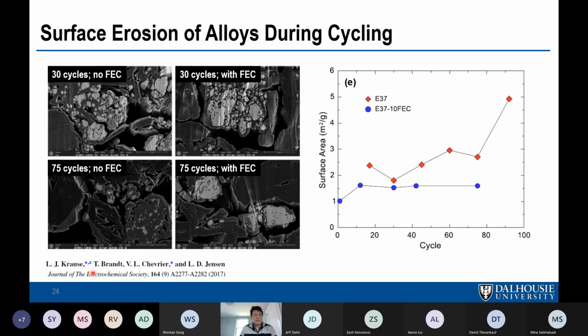This is a paper by Larry Krause and Vincent, and I don't know, Brandt. That's after I left, and Lowell Jensen. But they were looking at this surface erosion, as I call it in our lab and in our publications, how the surface of these alloy materials are eating away during cycling. These folks measured the surface area of these materials, which is a nice way of measuring this during cycling. And you could see with FEC, the surface area doesn't almost increase at all. If you don't have FEC, then the surface area increases a lot. But still, even with FEC, the surface of the alloy is slowly getting eroded away during cycling.